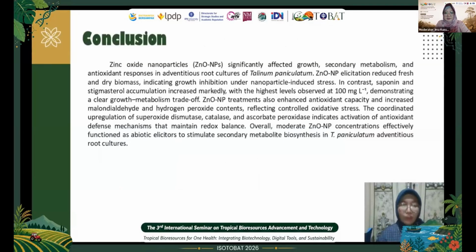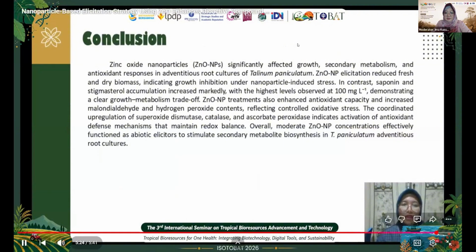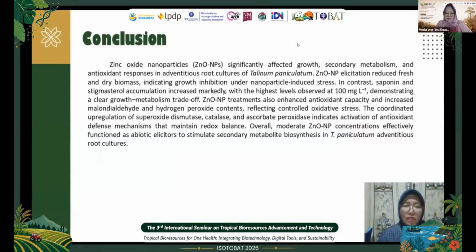culture. Conclusion: zinc oxide nanoparticles significantly affected growth, secondary metabolism, and antioxidant responses in adventitious root culture. Elicitation reduced fresh and dry weight biomass, indicating growth inhibition under nanoparticle exposure. In contrast, saponin and stigmasterol accumulation increased markedly, with the highest level observed at 100 mg per liter.